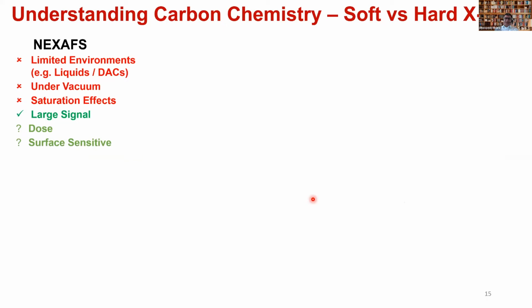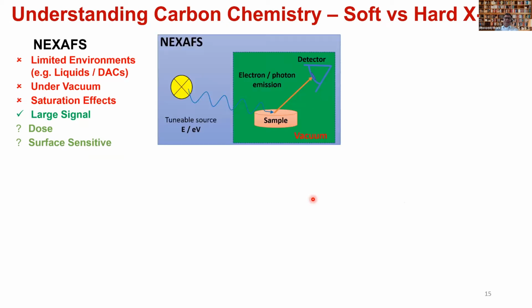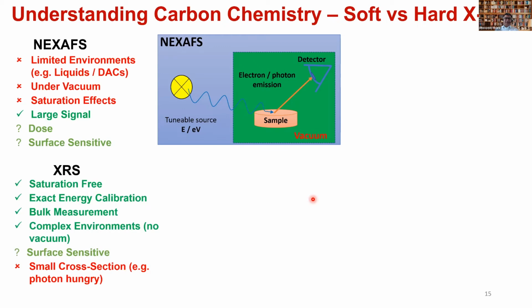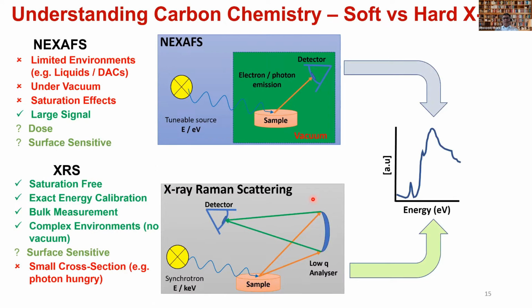bulk versus surface carbon chemistry. And so we use soft and hard X-rays. In this case, we use NEXAFS to try to understand what's happening on the surface. The advantage of NEXAFS is that it has a very large signal and is relatively easier to make measurements. However, XRS also gives some very important advantages, such as that it is saturation free, it can do bulk measurements, and it can also be performed in complex sample environments, so to say.